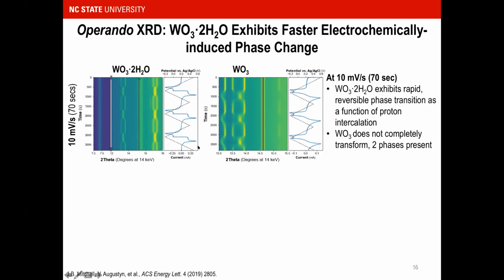And on the right-hand side is the electrochemical input and the current that we're measuring from the material. So we're really measuring this in real time at charge-discharge times of 70 seconds. For the hydrated material, we see this beautiful reversible phase transition that takes place as a function of proton intercalation, whereas in the case of the anhydrous material, you see that it never completely transforms into its protonated phase in the time scale that we're investigating.